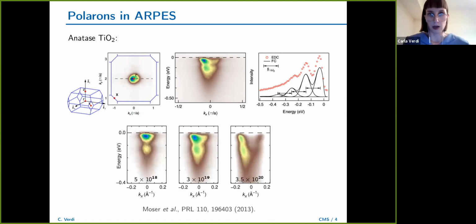And there is more. If you measure the spectra at different doping levels, at different carrier concentrations, you will see that the ARPES map has an interesting evolution with the doping. So you go from a low doping behavior where you have quite clearly the main band and the satellite and the tail, then similar at intermediate doping, and then at high doping, you have basically something that is more like a kink in the band structure.